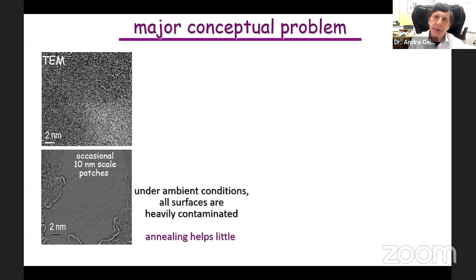Before I go to the properties, I'd like to point out that there is one major conceptual problem when you deal with van der Waals assembly. Because anyone who has looked at graphene, for example, in a transmission electron microscope knows that graphene is this honeycomb lattice. It's nice to draw pictures, but if you look in a microscope, even in ultra high vacuum, you'll find out that this monolayer is covered with hydrocarbons, with water, even in high vacuum. Annealing doesn't help, because all surfaces under ambient conditions adsorb atoms, especially hydrocarbons. And it's very rarely you can see clear patches where you can see a carbon lattice. It's graphene here, but mostly it's covered like that.